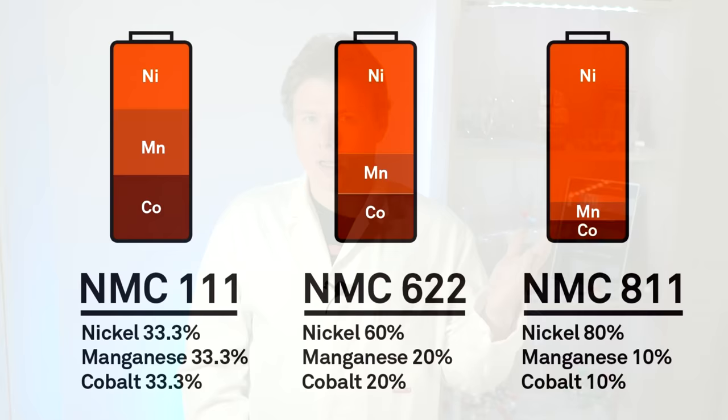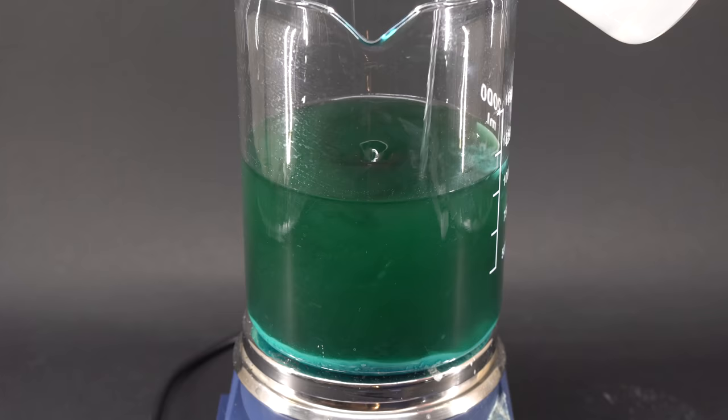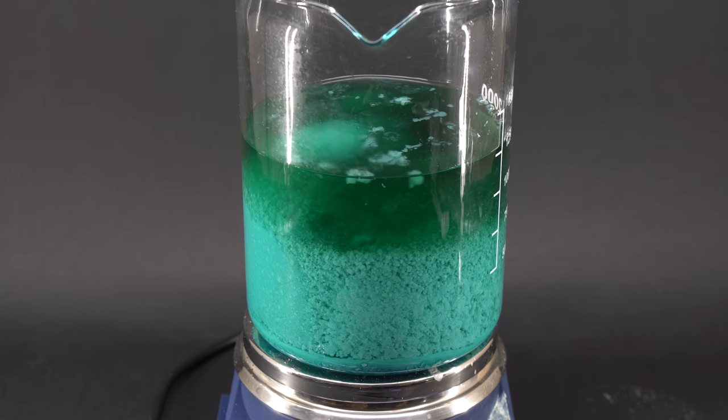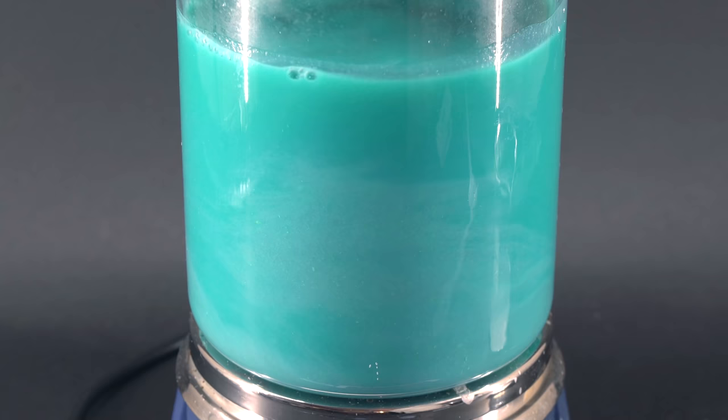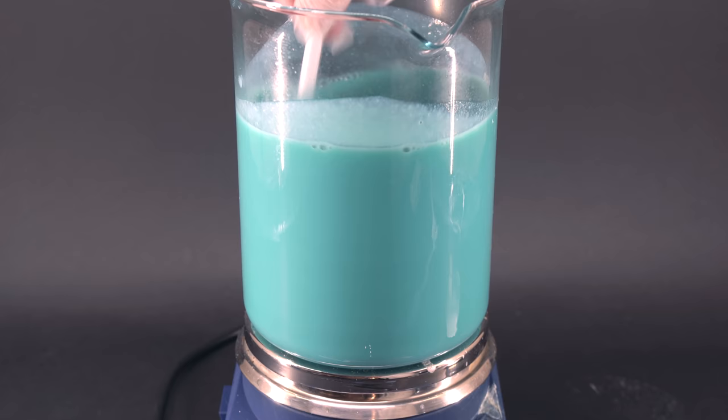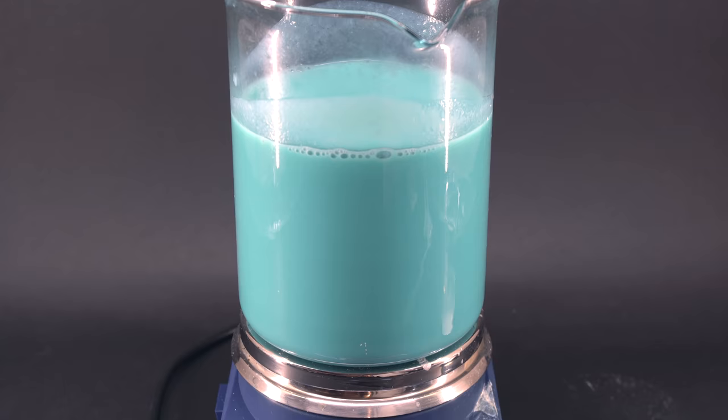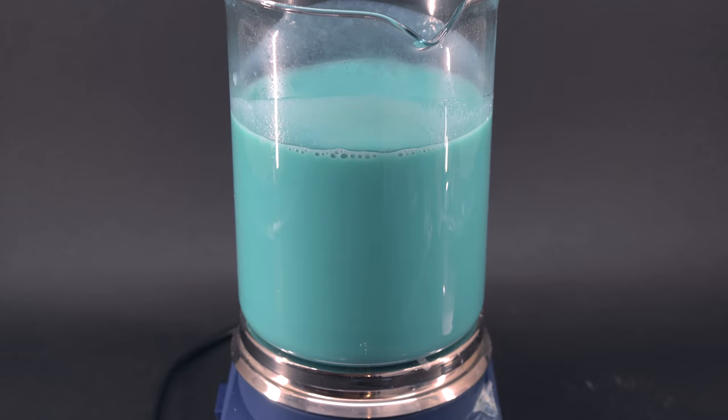I think there is very little of the precious red cobalt. Looking at the compositions of modern cathodes for lithium-ion accumulators, it becomes clear that most probably I have got either the newest ones or the previous models, where most of the expensive cobalt oxide is substituted with cheaper nickel and manganese. Thus, such batteries are cheaper to manufacture and have higher capacity. That is why, in order to separate the remaining nickel and cobalt from precious lithium in my solution, I'm just pouring concentrated sodium hydroxide solution into my beaker.